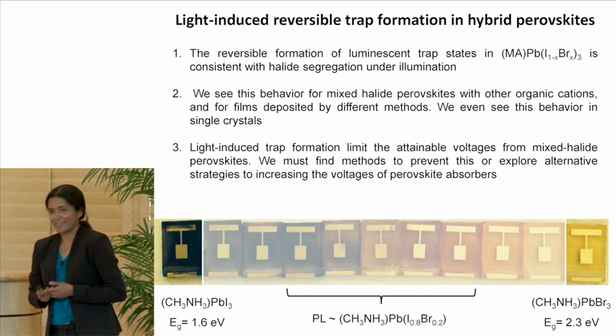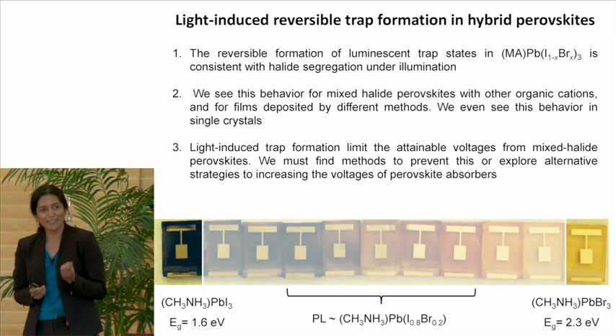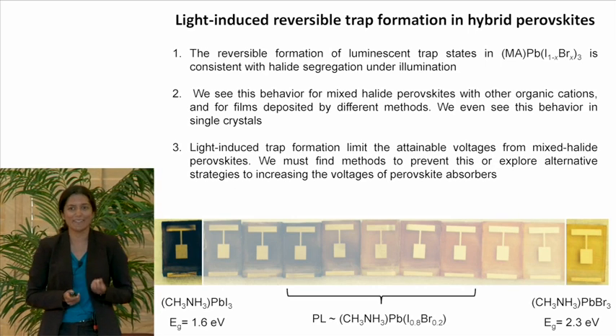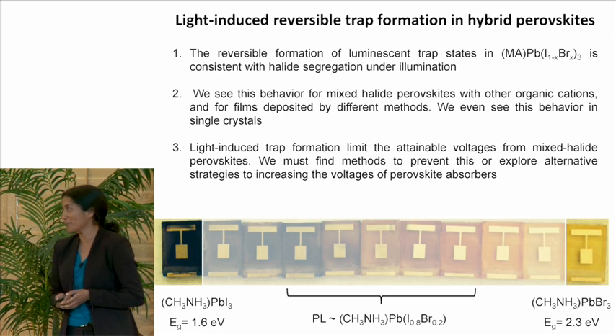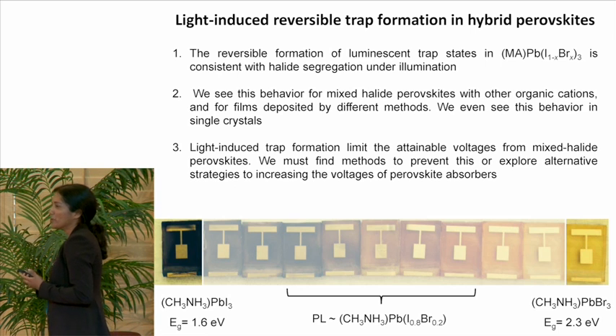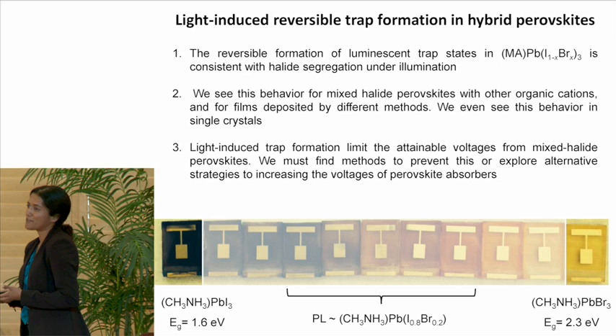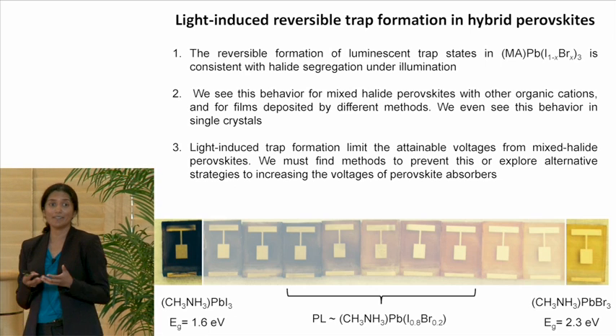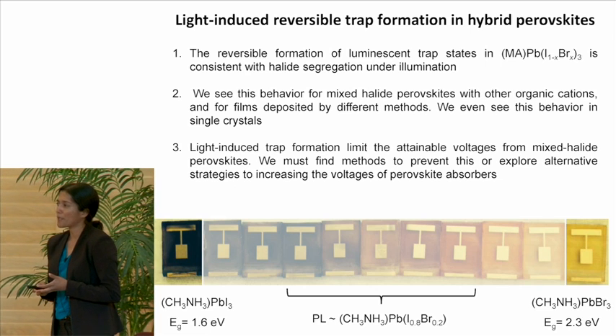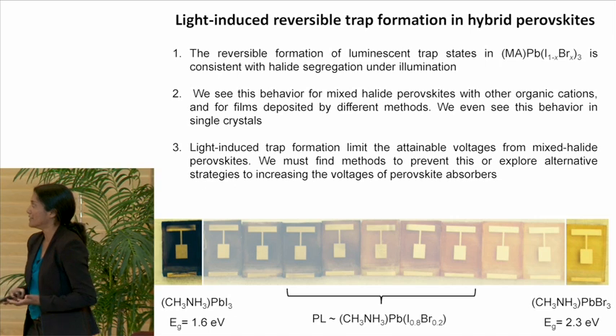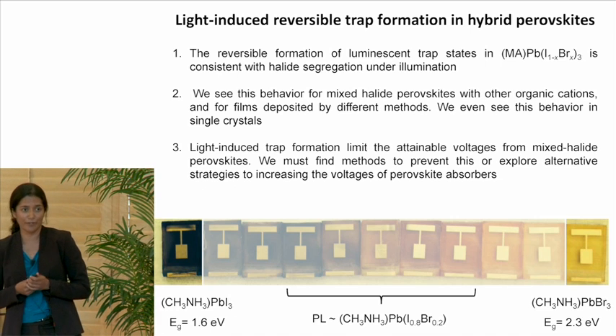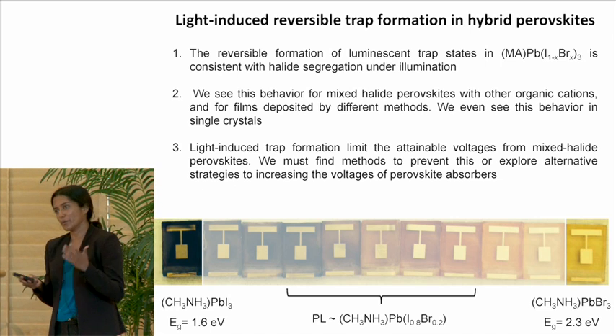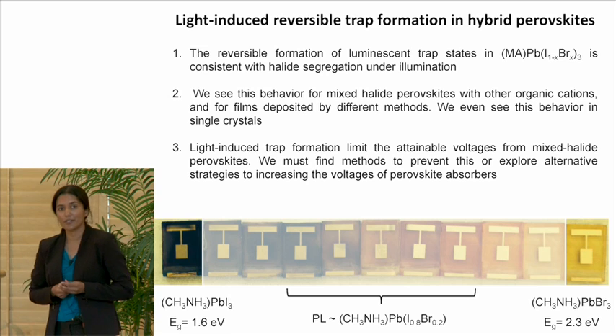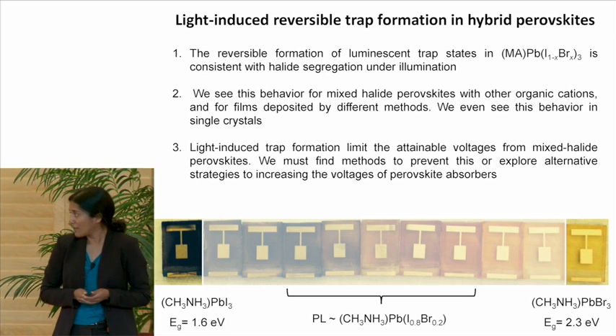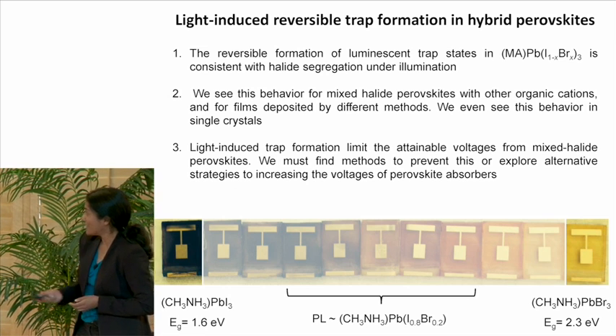And though I think this is incredibly cool, in terms of solar cells, this restricts the voltages that you can obtain from mixed halide perovskites. And if you really do want to form higher voltage perovskites, we need to either try to prevent halide segregation in these materials or look at alternative strategies to increasing the band gap. So for example, changing the metals or working with the lower dimensional 2D materials that I talked about previously. And I'm out of time, so I'll end there.